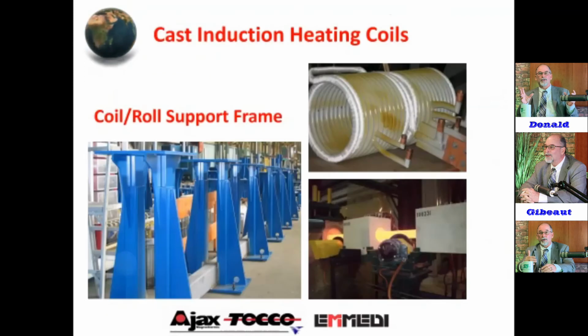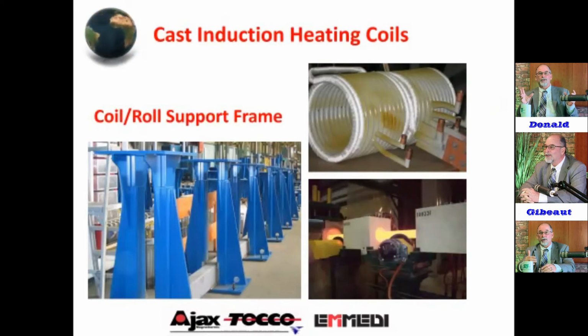So, you get into the induction coils. The upper right is a coil that is encased in refractory, as you see in the lower right, that you've seen on our lines heating. But this is what's inside of there, and it's fluidized bed coated or electrostatically powder coated with a nylon, and then encased in what we call a cast brick coil. And we did that because once upon a time, all of the coils had end plates and a mechanical structure. And the end plates that see all the heat and the thermal stresses were made out of asbestos. Well, that's been outlawed in most manufacturing, just about all, I think.